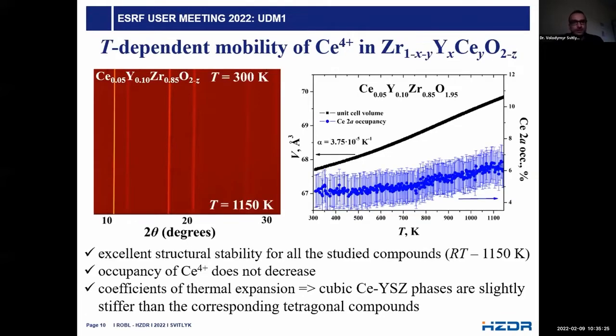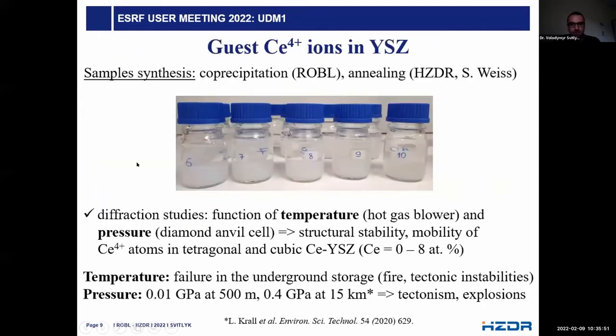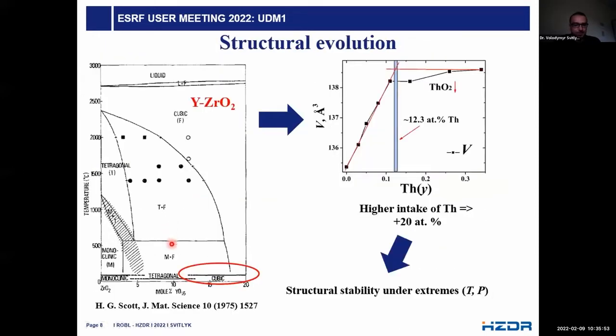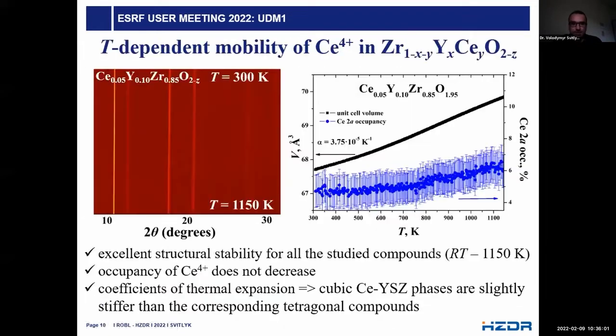So as concerns temperature, all of the studied samples, 10 in total, 5 for tetragonal symmetry and 5 for cubic symmetry, exhibit excellent structural stability as a function of temperature up to the maximum studied temperature of 1150 Kelvin. You see here, you have this tetragonal splitting, and it remains even at 1150 Kelvin, and even on cooling. It's quite remarkable because here you crossed twice this portion of the phase diagram where you have formation of the monoclinic phase. So really this phase is stable as a function of temperature.